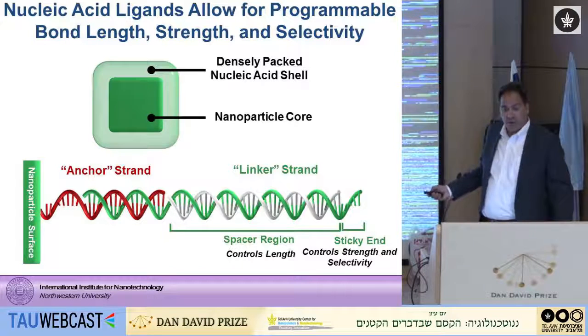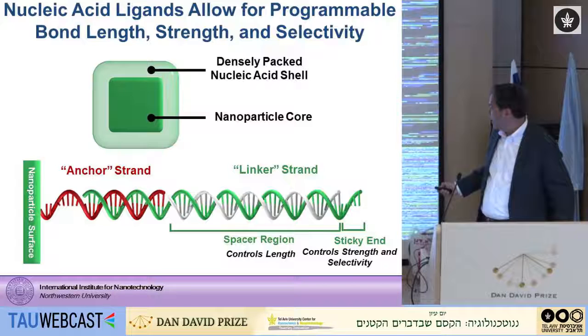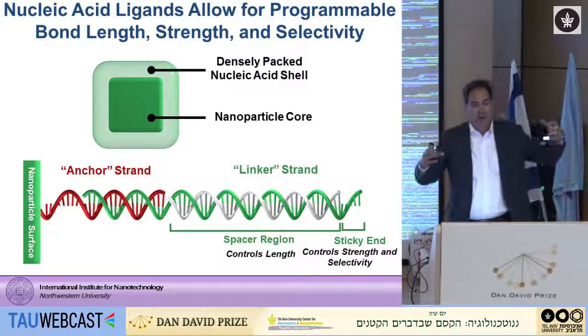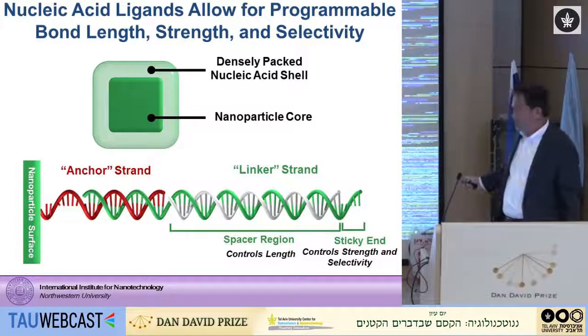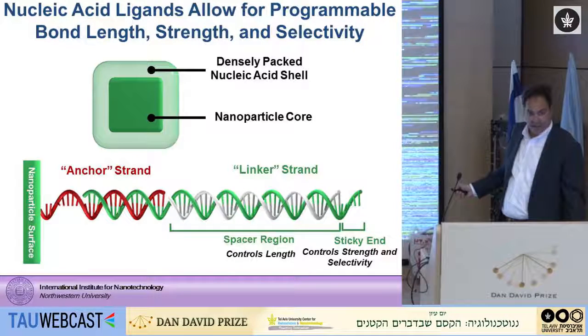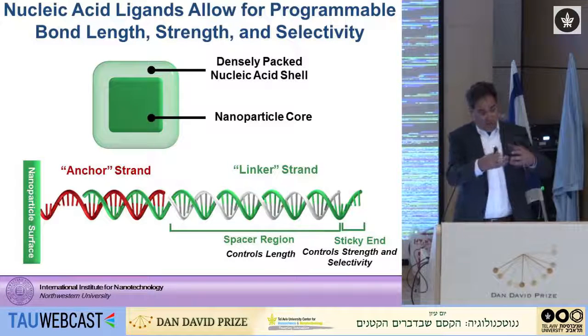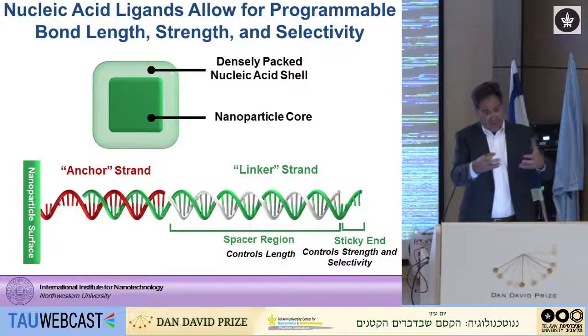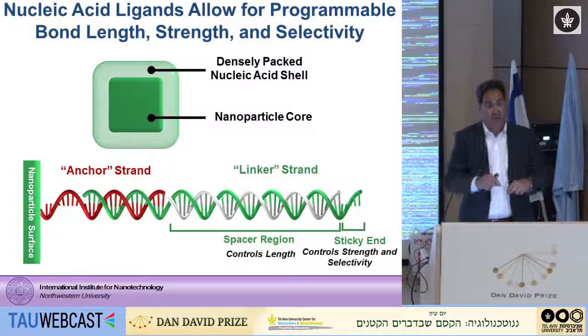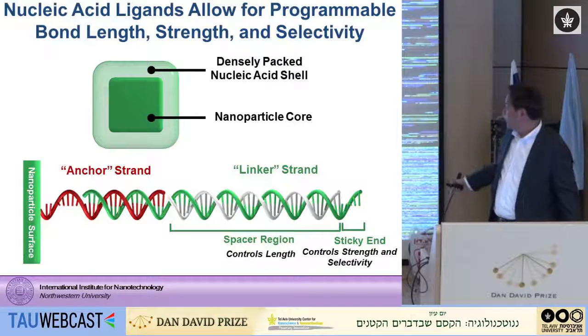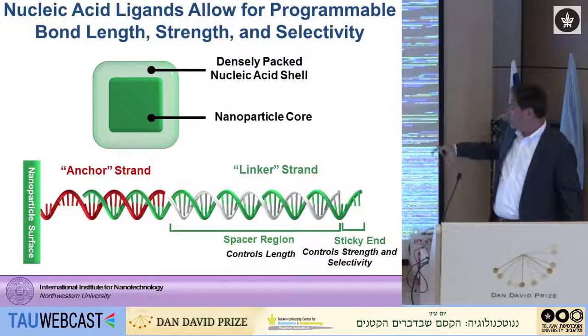But the bond's important. And you can see here we have an oligonucleotide, in this case a duplex connection, with a sticky end here. That's a single strand there. That's our recognition element. Those bases program what the particles recognize. And you can see this is really quite short compared to the rest of the structure. That was actually one of the important insights we made in the 2000s. You need a system that is strong enough in terms of holding the particles together, but weak enough that you get fast on-off rates and can equilibrate and fall into these thermodynamic sinks. You need a rigid structure, but you also need some flexibility built into these systems. And so you can see there are breakpoints here. We have an anchoring strand, which allows us to attach it to a particle.